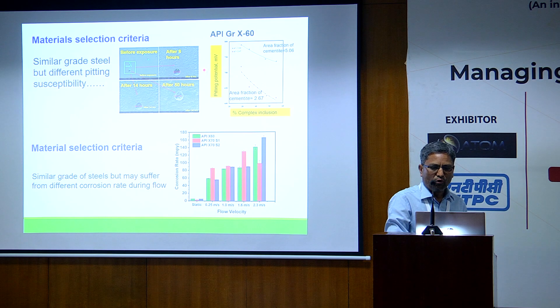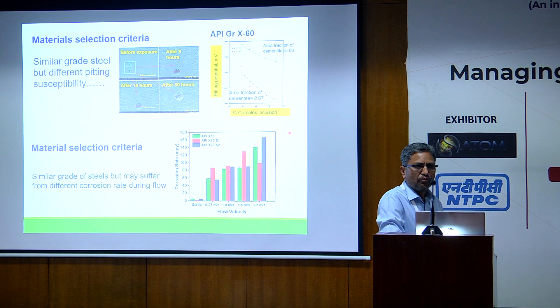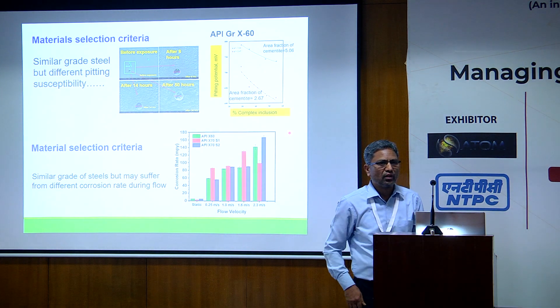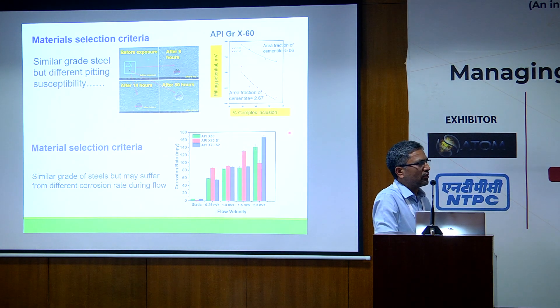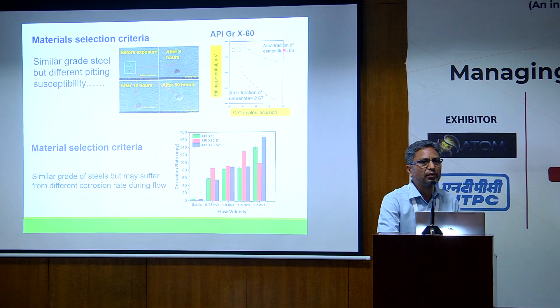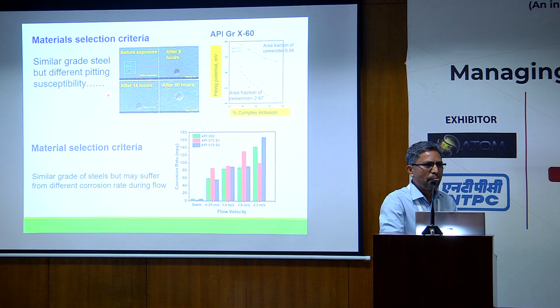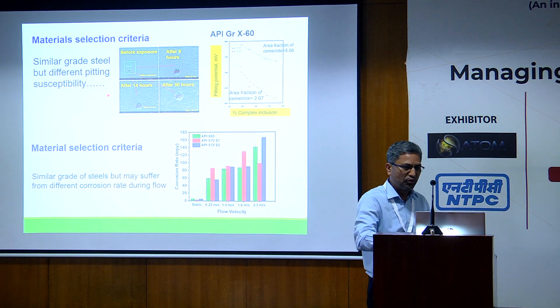This graph shows how pitting susceptibility varies with complex inclusions. With improving inclusion engineering in steel making, we have much less MnS-type inclusions, but we now have complex inclusions — an inner core of alumina with outer CaS or MnS compounds — yet those are still corrosion prone. We have shown that with different area fractions of cementite, for example 2.67% or 5.06%, the variation with complex inclusion differs. Higher pitting potential means better corrosion and pitting resistance. So while the grade may be the same, steel from different sources may not have similar pitting resistance — and this slide demonstrates that.